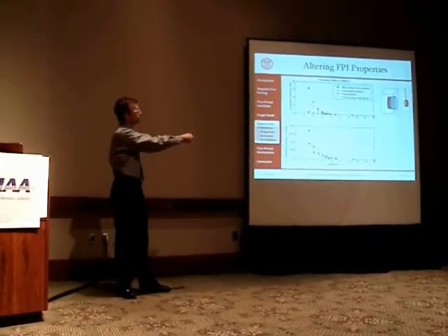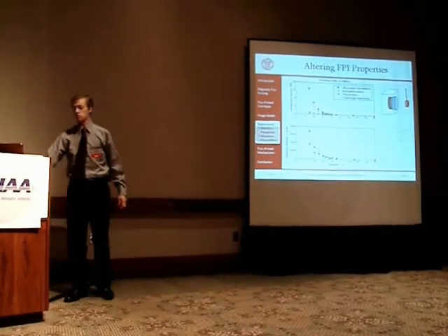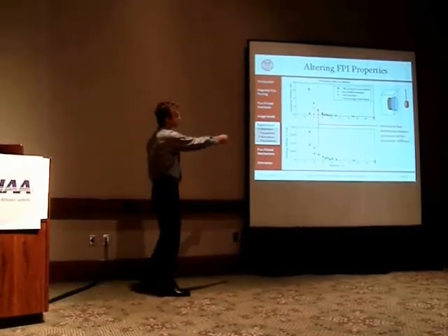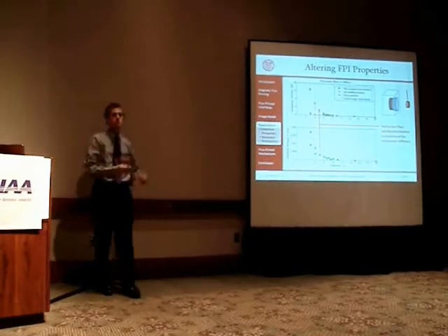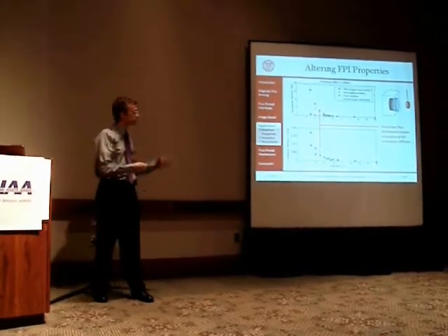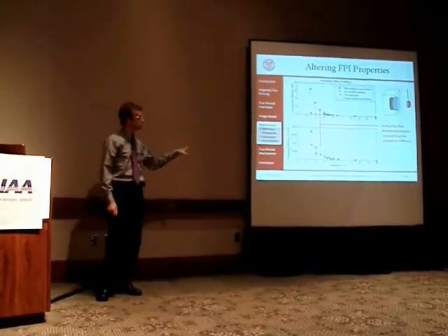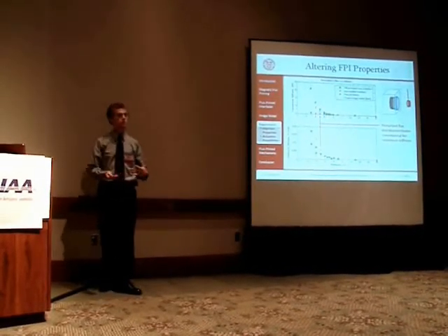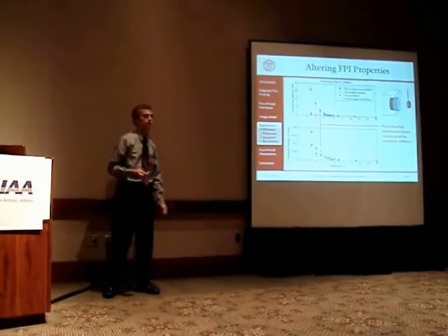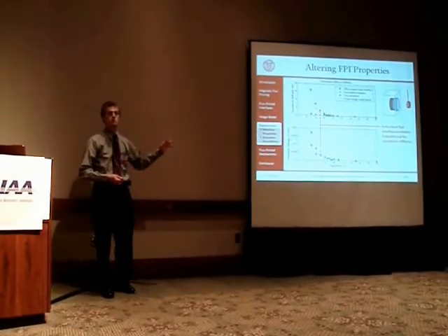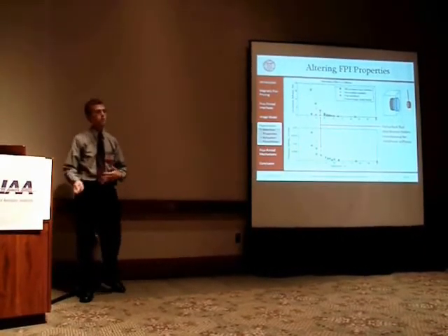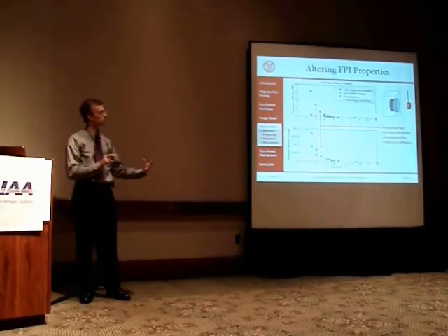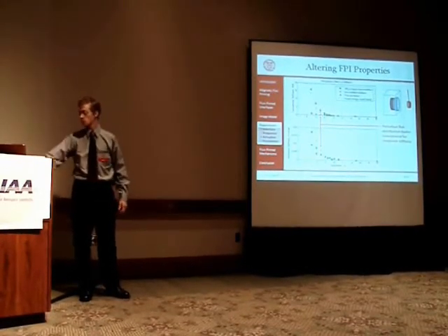And it turns out that when we do that, we get a sort of trade-off in stiffness. The translational stiffness drops a little bit, the rotational stiffness is boosted a little bit, and we're still characterizing this. But the gist here is that with some distribution of ferromagnetic material or material that has a magnetic response, you can alter the stiffness of this interaction, and you can get an interface that has certain desirable properties.